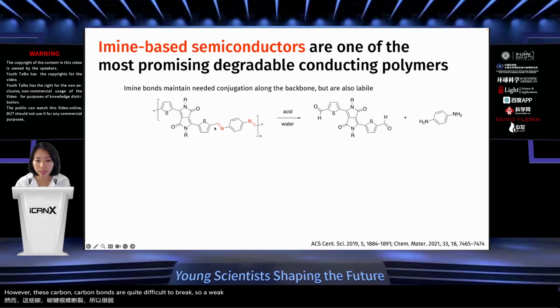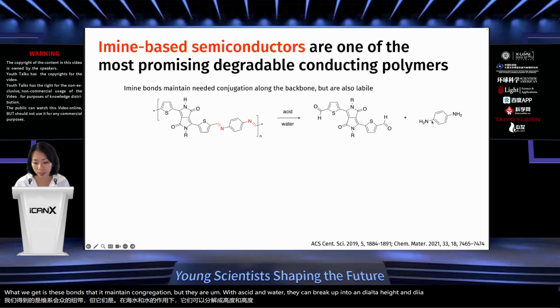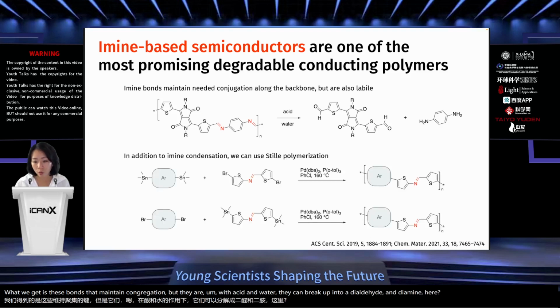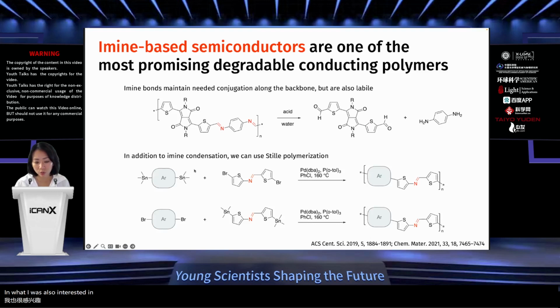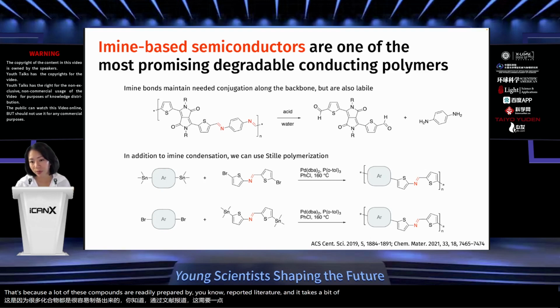So if we replace some of the carbon-carbon double bonds with a carbon-nitrogen double bond, what we get is bonds that maintain conjugation, but with acid and water, they can break up into a dialdehyde and diamine. And what I was also interested in was trying to make a lot of these types of polymers, but in a modular fashion. That's because a lot of these compounds are readily prepared by reported literature, and it takes a bit of time to make the dialdehyde.